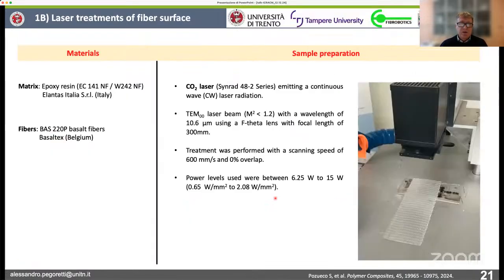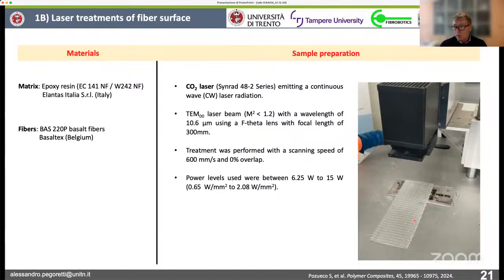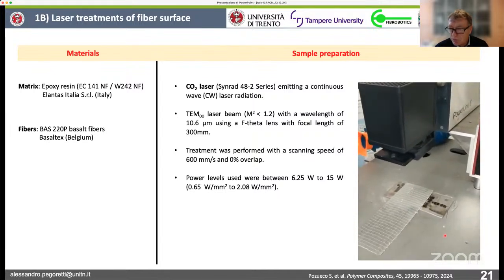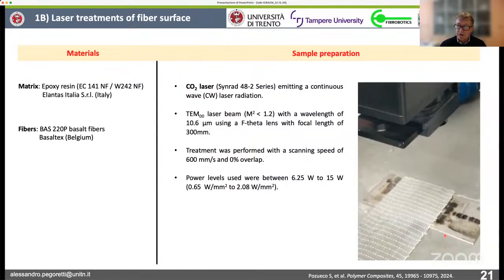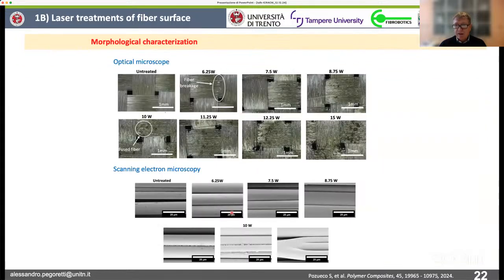Another possibility is to use laser treatments. Here we use basalt fibers. This was a collaboration with some colleagues in Finland and also in Spain. Here you can see the treatment of the basalt fibers or glass fibers. We use both of them, but the study mostly focuses on the basalt fibers. The scanning can be performed in a relatively fast way, and the power of the laser can be changed. This of course leads to different effects on the fabric.